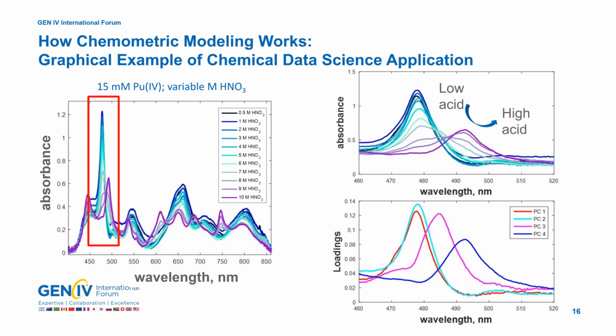And what we're looking at here are the principal components our model pulled out. In this case, our model said you really need 4 principal components in order to define all of the variability happening in this series of spectra. And it shows us these principal components as a function of our loadings. Now, a loading essentially indicates how important response is at a particular wavelength. A loading of 0 means not important, and a loading with magnitude means more important for quantification of plutonium-4.